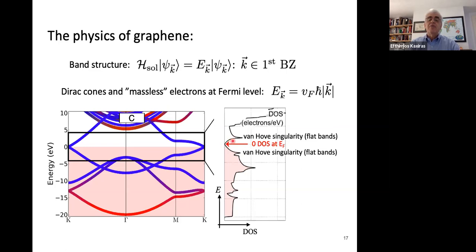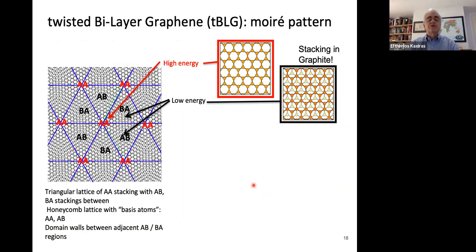If you go away from the Fermi level, you do get significant density of states, the so-called Van Hove singularities, which correspond to flat bands. But these are very far from the Fermi level, several electron volts. So it's impossible to access these regions just simply by doping the material. And you do want high density of states in order to be able to manipulate the properties of the device. So let's go to the twisted version of graphene, twisted bilayer graphene, and the moiré pattern that I was mentioning earlier.